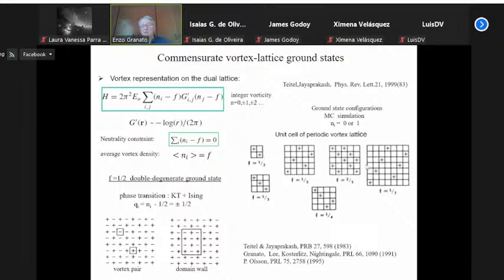There are, in fact, different transitions for different values of f. The case which has been mostly studied, besides f equal to 0 of course, which is basically the Kosterlitz-Thouless transition, is the case when the frustration is equal to 1/2. And for this case, the ground state is doubly degenerate, as illustrated here in the figure, in which the plus indicates the positive vortices and the minus the negative vortices. And there are two kinds of excitations of the ground state. You can identify this with a spin, so that you can flip the sign at one point, and flip the sign at another point. So this corresponds to a vortex pair in a background which has roughly zero vorticity.